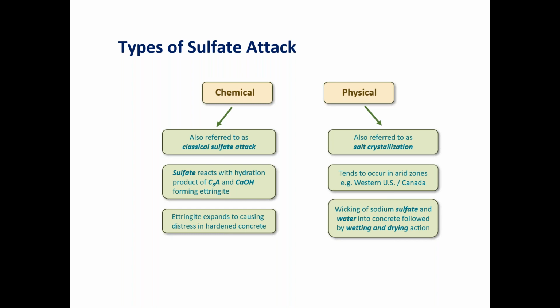And then over time, what happens is that these sulfate crystals form, and then they dissolve, and then they reform, and over time you get an expansion and contraction type of mechanism that eventually leads to cracking, and it can be a very quick, very rapid type of formation. I remember being in Arizona at a rest stop, and this rest stop was probably about 3 years old, and I'm looking at the concrete, the sidewalks, the walkways, and there were these cracks all over it, and I thought, well, that must be what they're talking about when they're talking about physical sulfate attack.